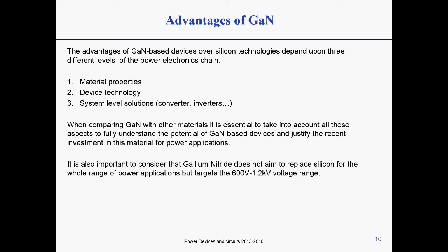We are not comparing gallium nitride as a piece of material compared to silicon. We are comparing a material with promising physical properties, such as wide band gap, low intrinsic concentration, and ones we've seen. And we are comparing at the same time the device technology, the heterostructure, so all the benefits that device gives us. And we are comparing GaN in the circuit itself, because we are using these devices in a circuit. We are not just taking the device as it is. We want to use it in a converter or depending on the application. We need to build a circuit around it. And if you consider that it can go much faster and the passive components can be shrunk, and the cost reduced because of that, then you see the advantage of GaN. So by summing up these three reasons, gallium nitride is actually a very promising material. And this is why at the moment there is a lot of effort in trying to crack the problems related to these devices.